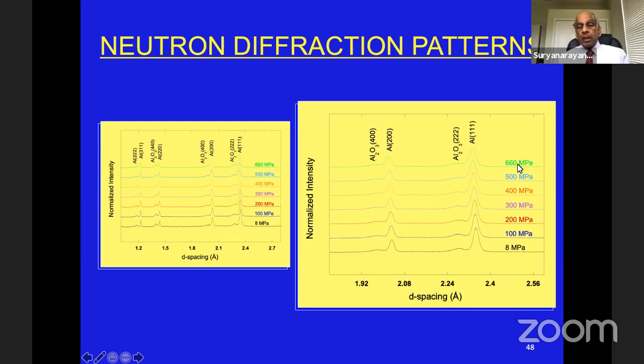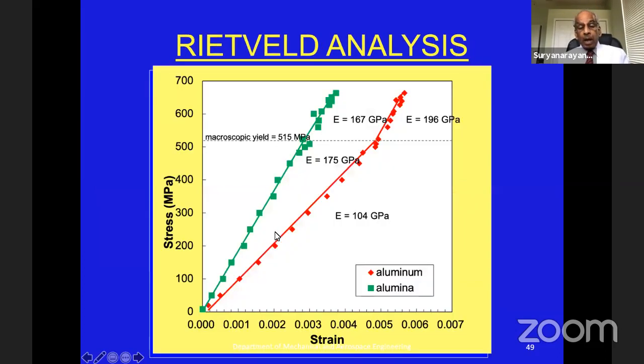You can get a stress strain plot, and once you get a stress strain plot, you'll be able to determine the modulus of elasticity. And now you would see here, if I plot this stress strain curve, for one, this is aluminum, the metal, and this is alumina, the reinforcement, you can now see beyond the macroscopic yield limit, there is a curvature change. Whereas here, there is a slight curvature in the opposite direction, indicating that the alumina is able to take up more load, but still not show much deviation from the linearity. That means the stiffness of this particular material is going to be quite high. So that's what we have to consider.